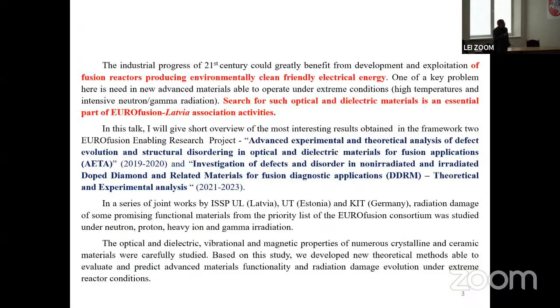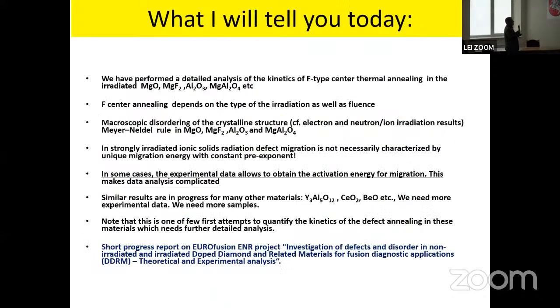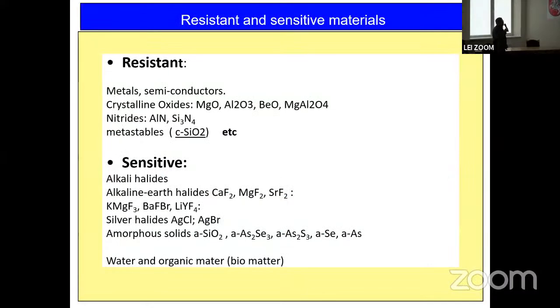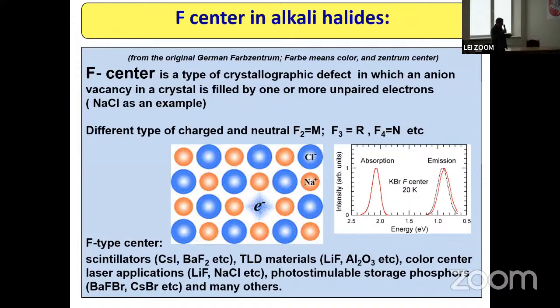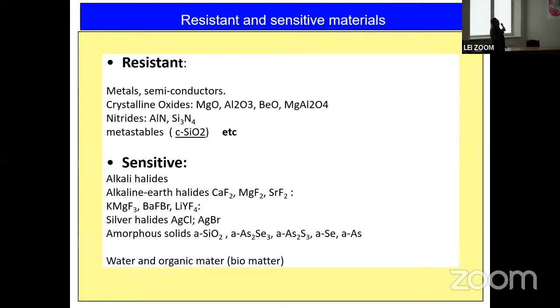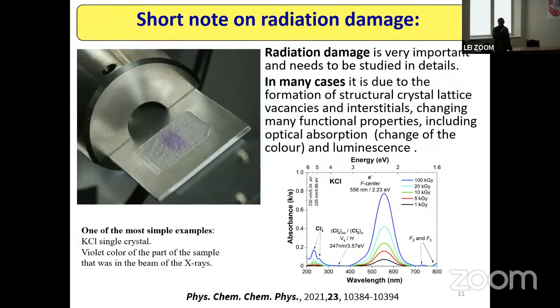So let me just shortly remind you that when we are talking about radiation resistance, some of the materials are very resistant, but some of them are not, because of just the chemical structure somehow. And this is important also for application. For some applications, we need a very resistant material, but for others, we need the opposite behavior, for detection, for example. And this is why I like this very much, because it's just an example of how we can see radiation damage in our laboratory conditions of a KCl crystal after quite strong irradiation with X-rays, and you can see the change of the color.